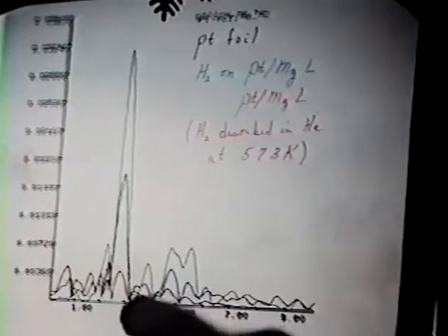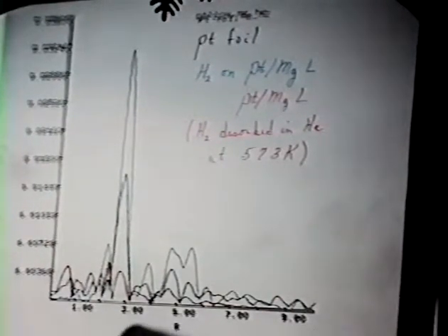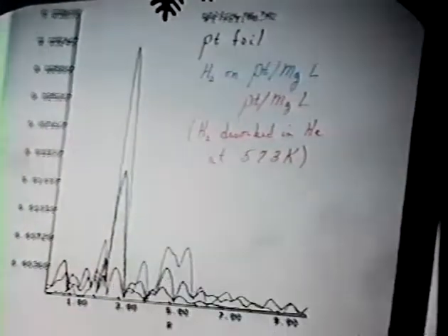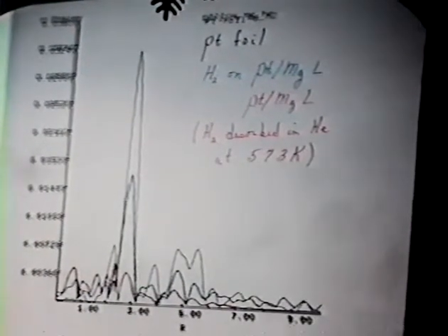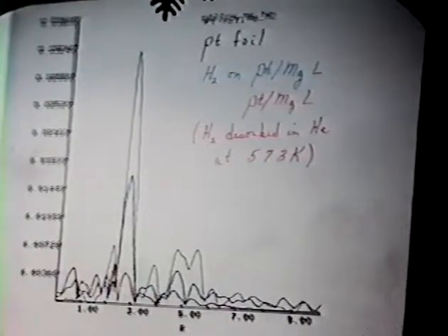If you take these particles where there's no coherence, expose them to hydrogen at room temperature, you reform the particles and see it in the XAFS. Now, another possible explanation. Suppose that when we swept the hydrogen off at 270 degrees with helium, we were careless, and we let in some oxygen.